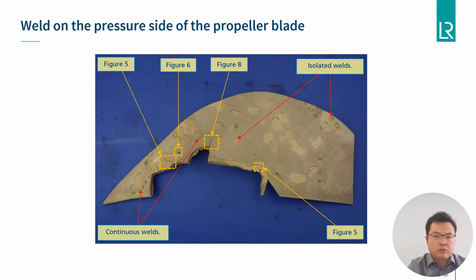Just as a reminder, some of the photos included in the presentation are directly copied from the investigation report, hence the quotation of different figure titles. For this case, they are simply magnified views of the squared area with highlights of unique contrast caused by either continuous welds or isolated spot welds. For example, figure 5 includes a crack associated with welds. The feature included in figure 6 is a shrinkage cavity, which is likely to form during the propeller casting process in manufacturing. And figure 8 is a secondary crack associated with cavitation.